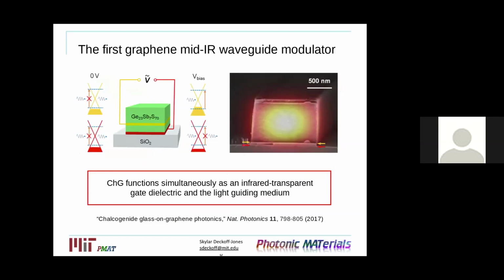And to show the merits of this method, I showed you the first device which I'm going to be discussing today, which is a graphene-based mid-infrared waveguide modulator. So the mechanism of this modulator: on the left you can see a schematic, and on the right is an SEM image of the cross-section of the device. We have 2 layers of graphene. So we have a bottom layer of graphene, and then we deposit a thin layer of chalcogenide glass, using it as a gate dielectric, followed by an additional layer of graphene, and then the remainder of the chalcogenide glass to form the finished waveguide.